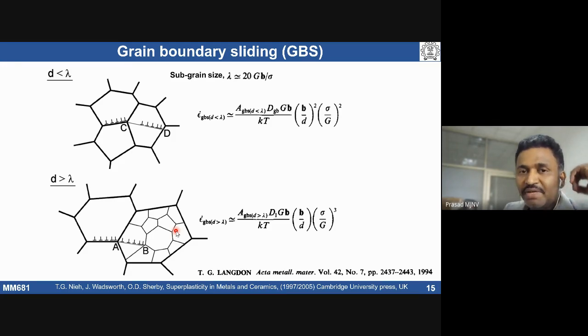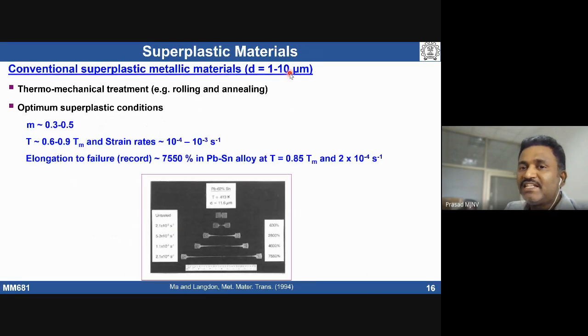Conventionally, when we talk about conventional superplastic materials, typically the grain size will be 1 to 10 micrometers. These grain sizes can be obtained by thermomechanical treatment, such as rolling, annealing, and forging. What people have observed for optimum superplastic conditions is an m value typically of 0.3 to 0.5 in conventional materials. The temperature at which superplasticity has been observed in conventional materials is 0.6 to 0.9 times the melting point, and the strain rates are 10 power minus 4 to 10 power minus 3 per second. If you deform material at this rate and in this temperature window, it can exhibit strain rate sensitivity between 0.3 and 0.5 and can exhibit superplastic elongations.